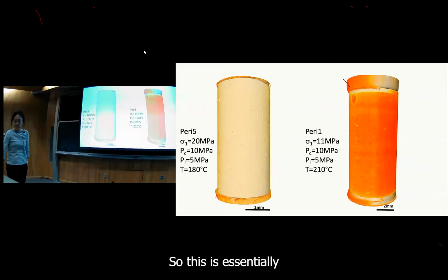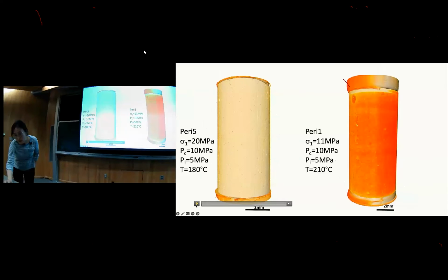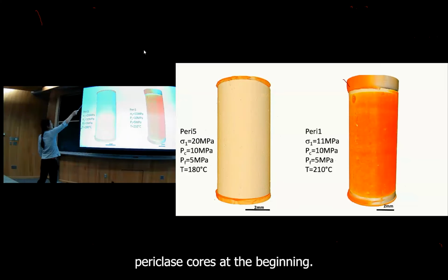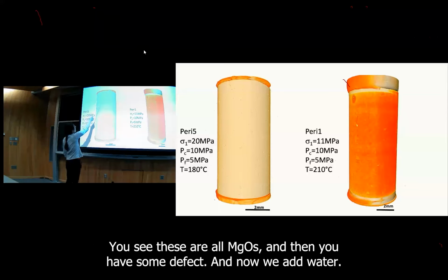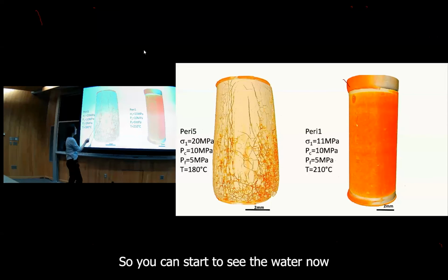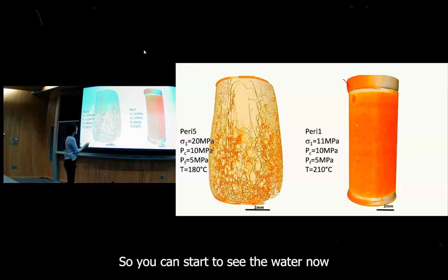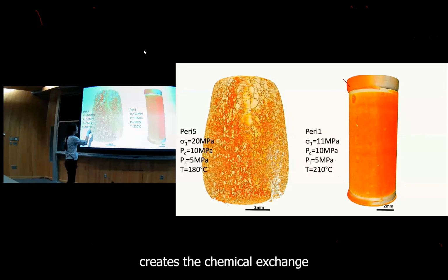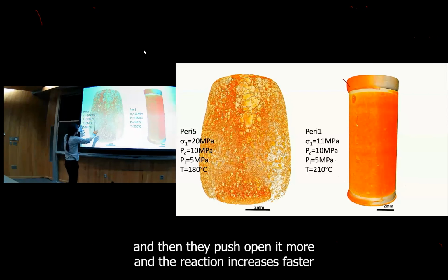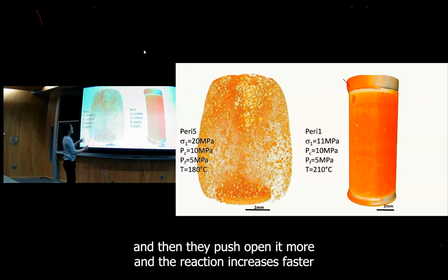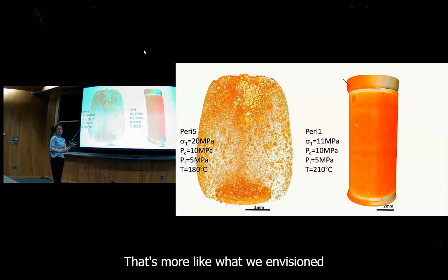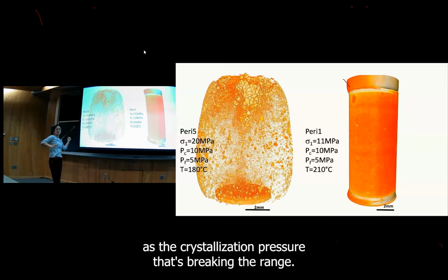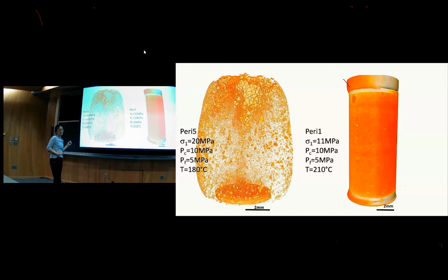So this is essentially what happens. This is one of the periclase cores. At the beginning, these are all MgO, and you have some defects. And now we have water, so you can start to see the water create the chemical exchange, and then they push it open more and the reaction increases faster. Eventually, this whole core, that's more like what we envisioned as the crystallization pressure breaking the bridge, all right?